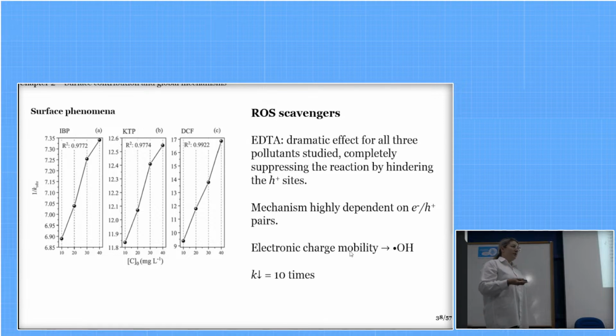In order to confirm the surface phenomena, we tested different concentrations of the pollutants and fitted them to the Langmuir-Hinshelwood equation model, and we observed a higher fit for diclofenac, which was precisely the one that showed a possible interaction with the surface. And we tested the ROS scavengers, which are added to scavenge these possible reaction sites on the surface of the catalyst. When we added EDTA, we observed that the reaction almost stopped. It was a dramatic effect, suppressing the reaction by hindering the h+ sites, so the electronic flow.